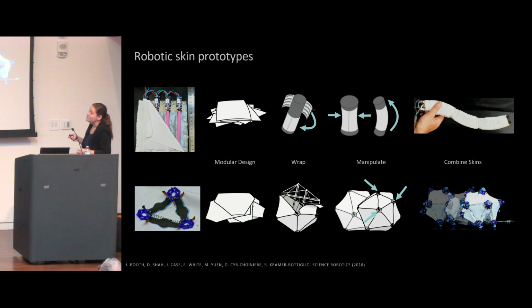And then instead of McKibben actuators, we use shape memory alloy actuators. So shape memory alloys, it's a metallic alloy that can go through a crystalline phase change between martensite and austenite when heated. It can be programmed to remember a shape. So what we do is we buy it in wire form. We just buy these wires, and then we program it to remember a coiled shape.